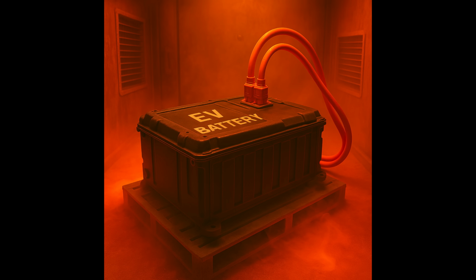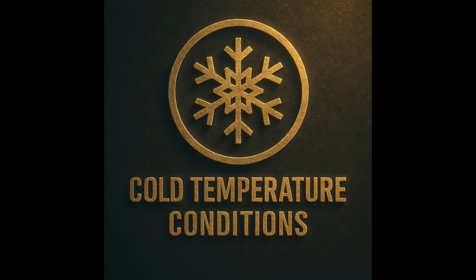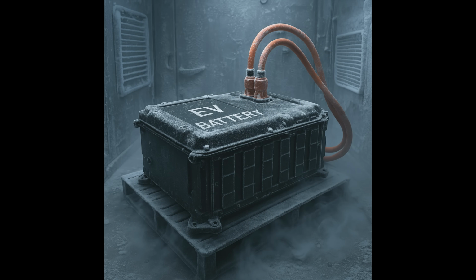Electrochemical stability. At high heat, you risk electrolyte decomposition. In cold, lithium plating becomes a risk, which can cause dendrites, leading to internal shorting. At low temperatures, the organic solvents in the electrolyte become significantly more viscous. Viscosity increases by an order of magnitude or more, slowing down the movement of lithium ions through the solution. This leads to poor ionic conductivity, which means reduced cell power output, slower charge acceptance, increased internal resistance, and the possibility of lithium plating.